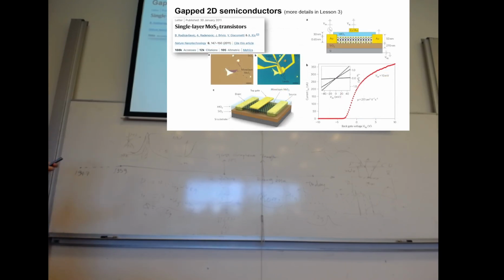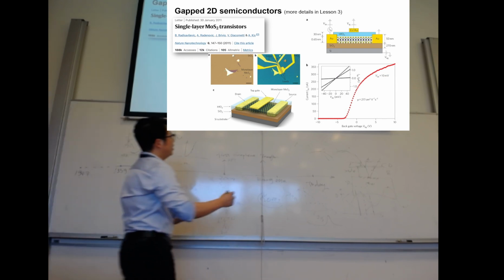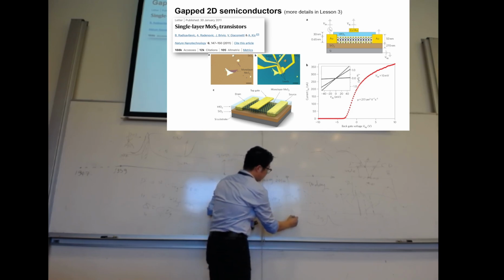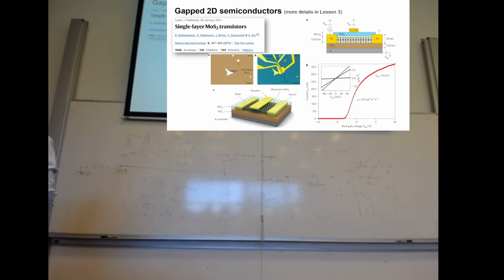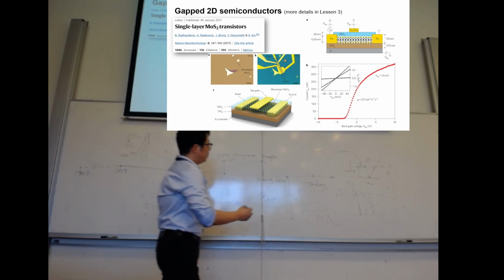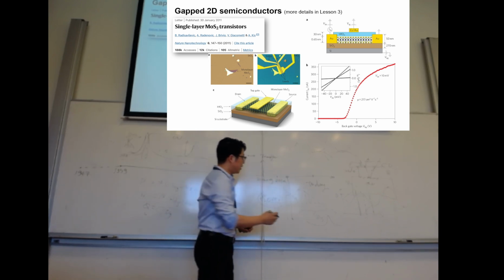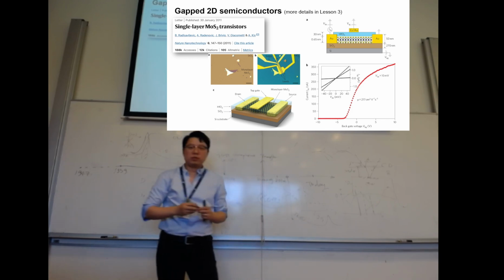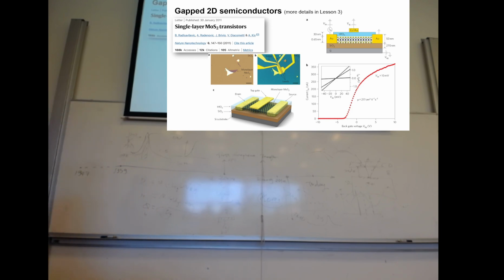And in the meantime, in 2011, somewhere here, people found that graphene is hopeless and graphene is useless. It has no band gap. It's not useful for any kind of real application. So a group of people headed toward another direction. They found that maybe transition metal dichalcogenides are the future. For example, this is a famous paper published by Kis in Switzerland. They found that using the same exfoliation method, with very thin, atomically thin MoS2, you can also construct transistors. Now there is no bipolar behavior. The off is really off, and the on is always on. It looks like a silicon transistor. So it might be really useful.